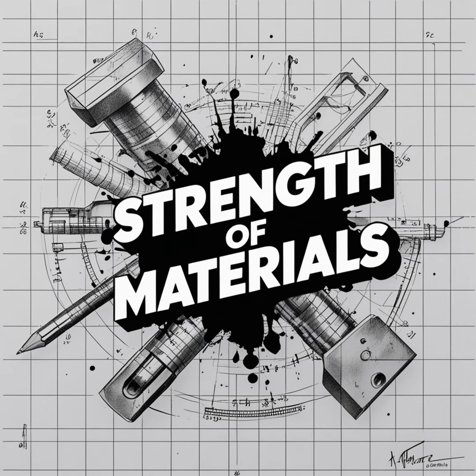If you plot both of those curves on the same graph, do they cross over? They do. They intersect exactly at what we call the transition life. It's the physical point where the elastic damage and the plastic damage are exactly equal. What does that crossover point actually mean for an engineer choosing a material to build a machine? It represents a brutal engineering reality. If your part needs a long life, if you are operating well past the crossover point in the high cycle regime, the elastic strain is completely dominant. Therefore, the strength of the material controls its performance. You want a hard, ultra-strong metal to survive.